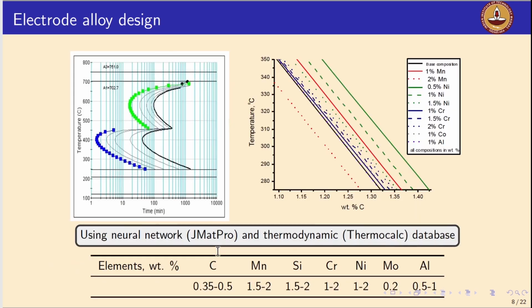So to begin with, we start by understanding the effect of alloying elements on the solid-state transformations. Right, so we use a combined mathematical calculation and physical simulation approach. So we identify some base chemistries which can give us a bainitic transformation at short time durations when we hold at isothermal holding. So for example, I show one such candidate chemistry, and we calculate the CCT diagrams using a commercially available neural network database and thermodynamic database, for example ThermoCalc, and we construct the CCT diagrams for this chemistry.